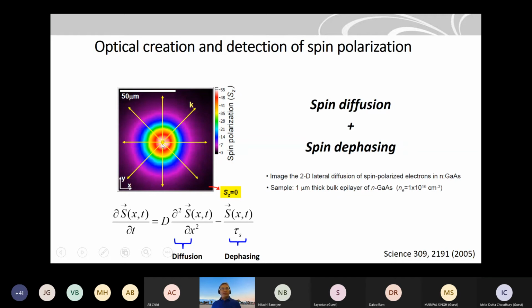So what you see here is spin actually diffusing. So you create spins, and in the semiconductor they diffuse because it's a non-equilibrium spin you created. So they diffuse in the material, and you see how spins are diffusing. So in the equation, how to find the spin density with space and time, you see that there's a diffusion term here. It's a diffusion constant, how spin density changes with distance. And the dephasing is the lifetime of spins in this material. Okay.